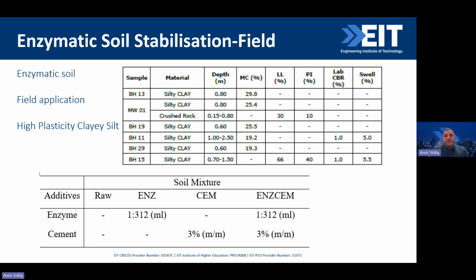Then we used the enzyme by itself at a 1 to 312 ratio, which is every 1 ml of the enzyme used for 312 ml of water dilution. And for the cement one, we used 3% cement. Then we have the sample of the enzyme and the cement together to test before going to the field. So we want to understand the behavior of that particular soil material with the enzyme, with the cement, and with the combination of these additives, for that particular soil material from the field.